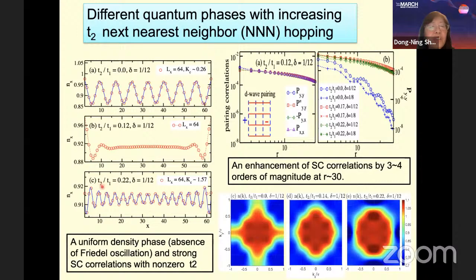If we go to even larger T2 over T1, we also obtain a stripe phase, but the period of the stripe is reduced from the smaller T2 over T1 phase. In this third phase, within each stripe we have 2 electrons. It turns out it's a common case that if we have each stripe with 2 electrons, superconductivity usually also emerges.